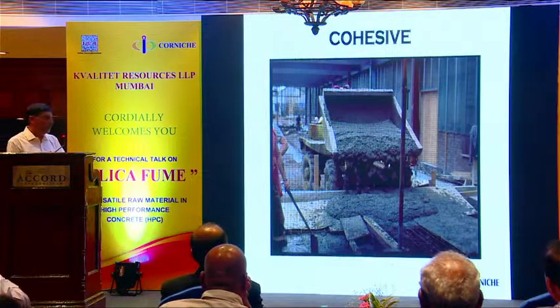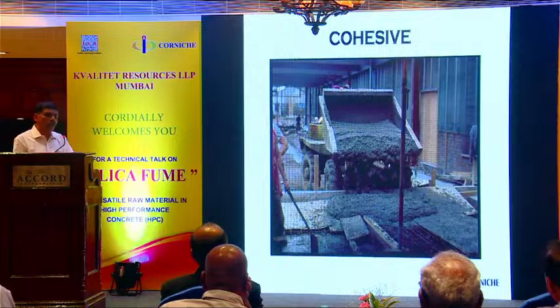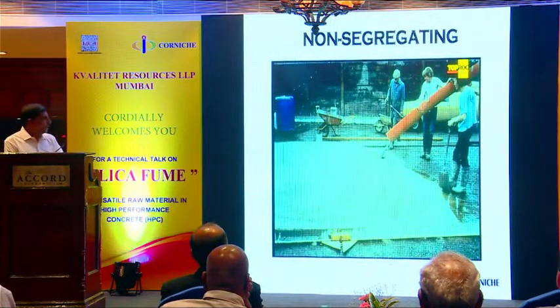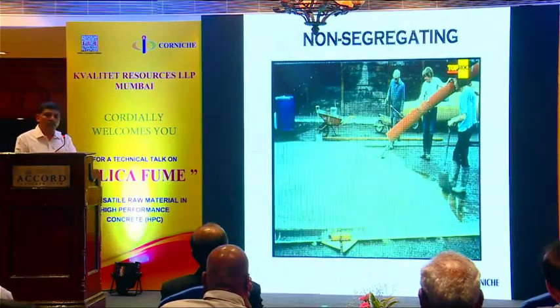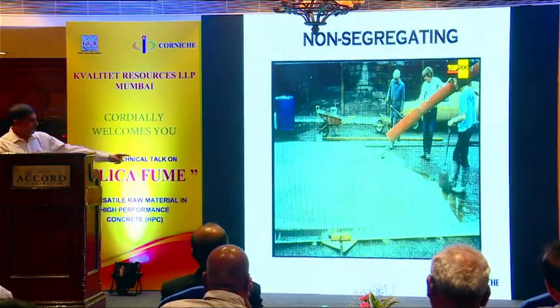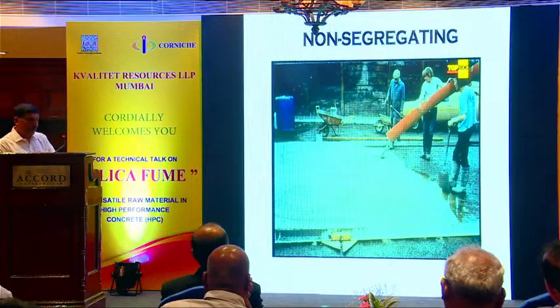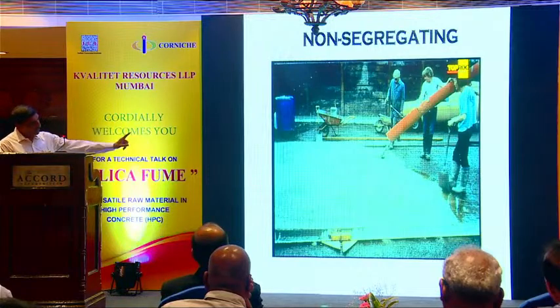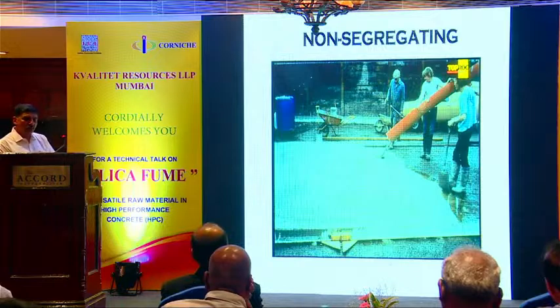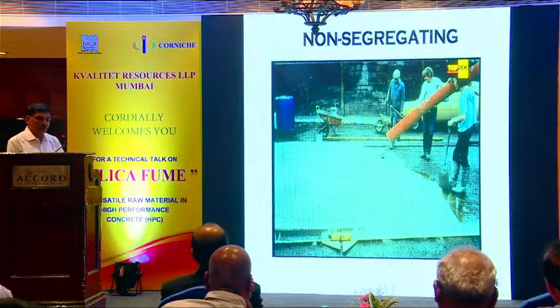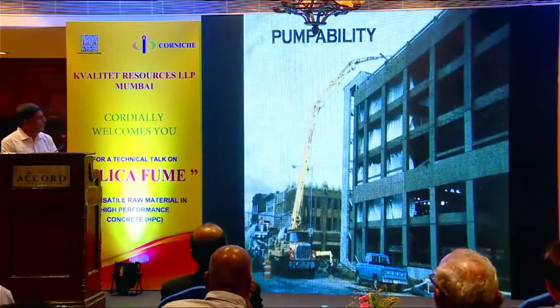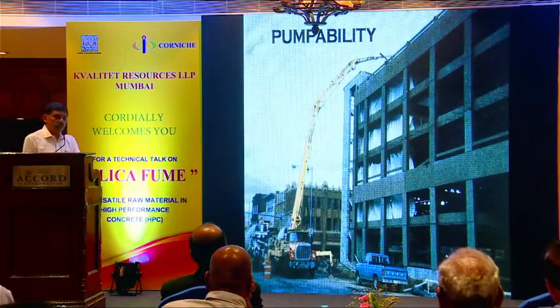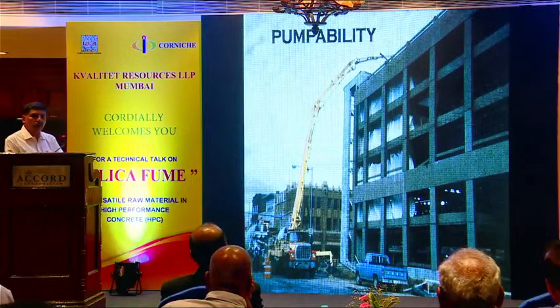Silica fume being spherical, it gives what we call a ball bearing effect to the concrete. Non-segregating, this is a 250 mm plus slump. Two things you observe: the formwork is not all that good here. Had it been an ordinary concrete, slurry would have come down from the bottom. And also the water standing on the floor is not getting mixed with the concrete. Silica fume concrete does not allow anything in, nor does it allow anything to get out. It can be pumped to various distances, various heights, no segregation.